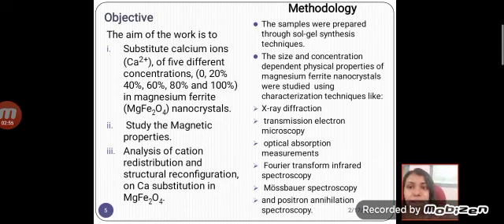So what is the methodology we have adopted? We have used a sol-gel methodology for the synthesis of the samples, and then the concentration dependent physical properties of the magnesium ferrite nanocrystals were studied using various techniques like X-ray diffraction, transmission electron microscopy, optical absorption measurements, Fourier transform infrared spectroscopy, Mossbauer spectroscopy, and finally the defect characterization technique, which is positron annihilation spectroscopy.